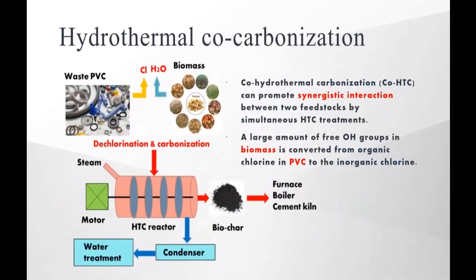In this presentation, we propose a hydrothermal co-carbonization process of PVC and biomass. Co-hydrothermal carbonization can promote synergistic interaction between two feedstocks by simultaneous hydrothermal carbonization. Biomass has a large amount of free OH groups. This OH group helps the conversion from organic chlorine in PVC to inorganic chlorine. As a result, carbonization of biomass also progresses by the elimination of OH groups.